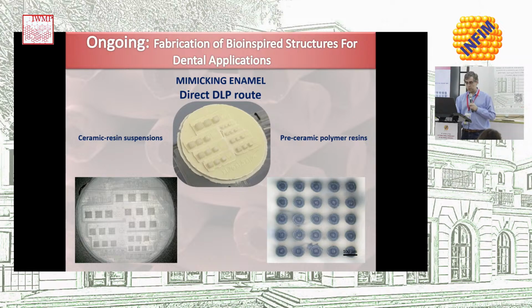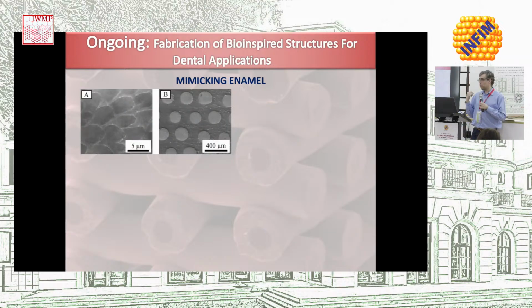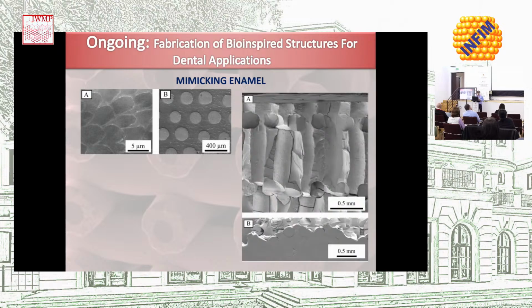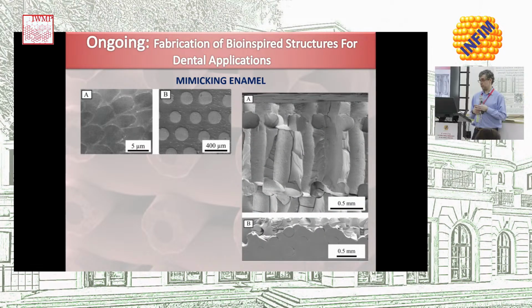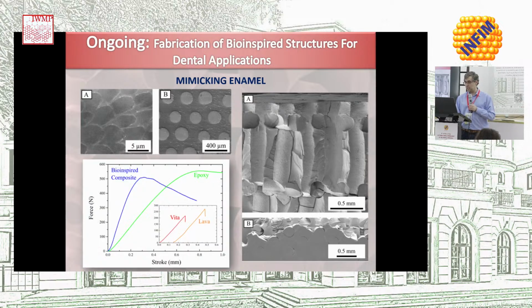Although this is still in progress, we still have to optimize the sintering and the infiltration process with the polymer later on. But preliminary work that we did already with robocasting structures shows that these materials, when we infiltrate them with polymers, do have a resemblance to enamel, and also show what we want, some toughening. As you can see, the fracture surfaces on these structures, even with this polymer that we use here, which is epoxy, which is very brittle, still show a rough crack surface, which means we are having some toughening effects.